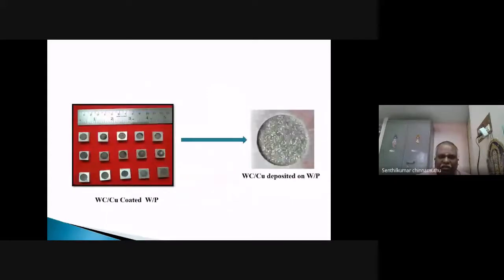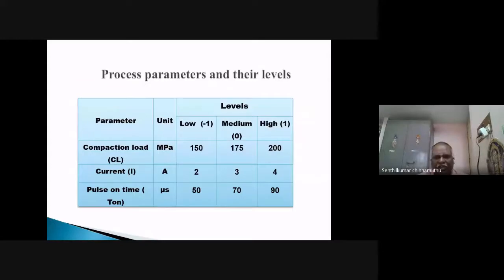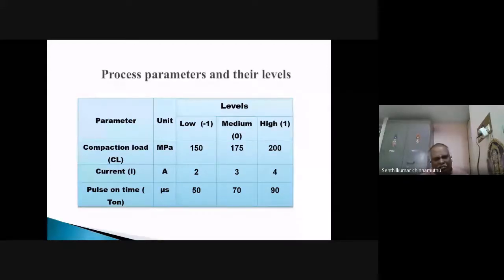See, these are the parameters which we have chosen. Various electrode discharge parameters are available: current, pulse on time, pulse off time, flushing pressure. But the current and pulse on time are suitable for electrode discharge coating. That's why we opt for these. And the compaction load is also considered for the coating parameters, that is, the surface modification parameters. The surface modification parameters are compaction load, current, and pulse on time.